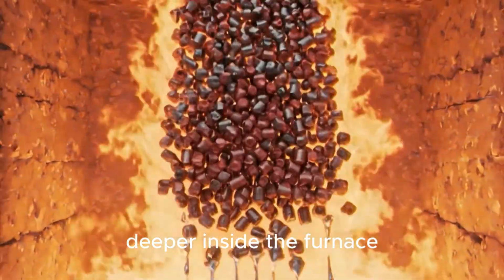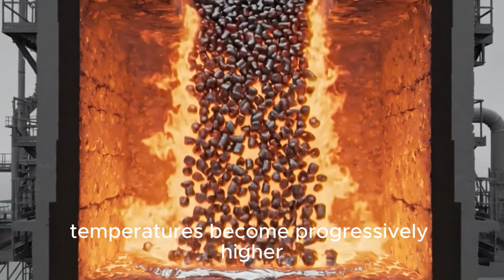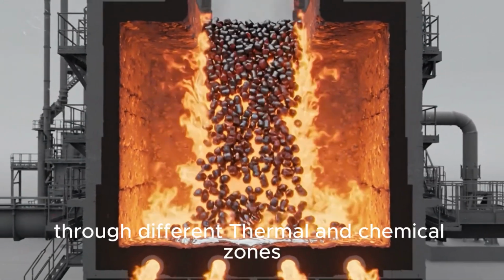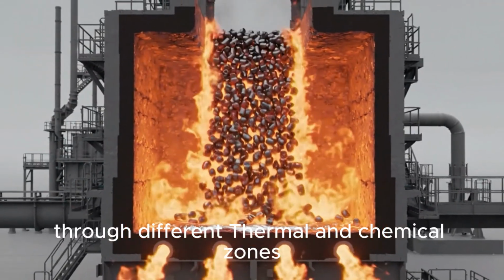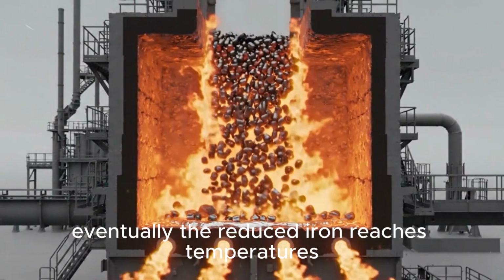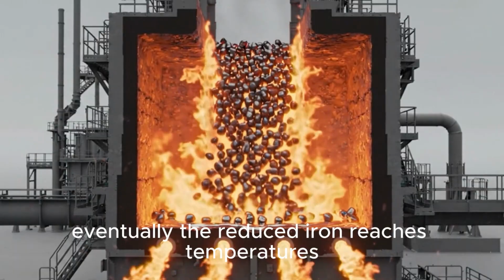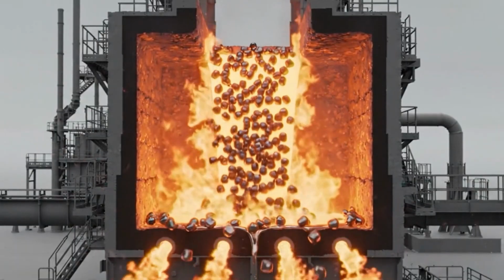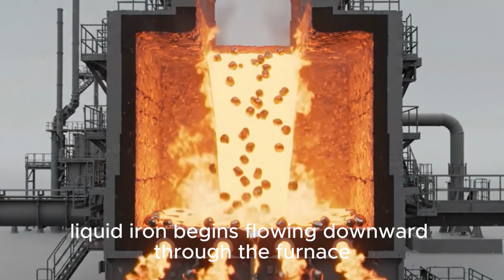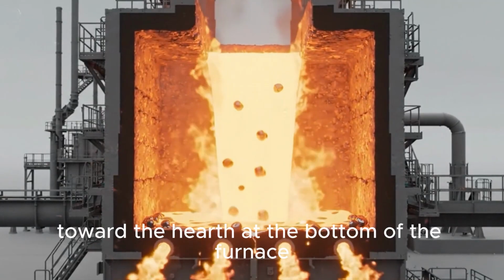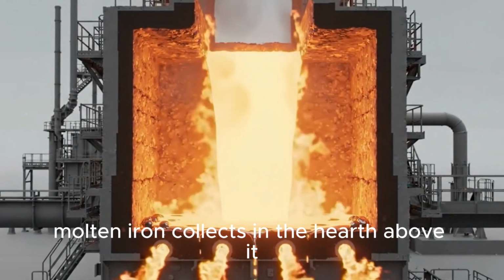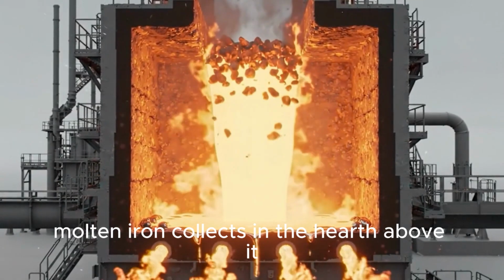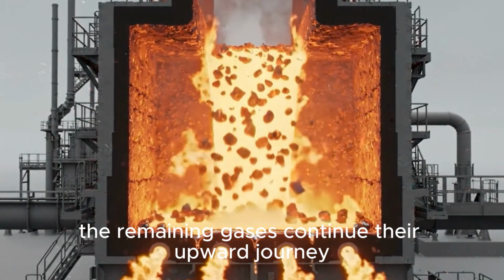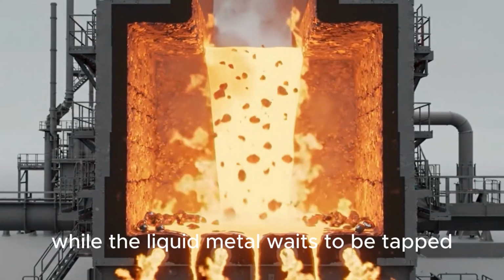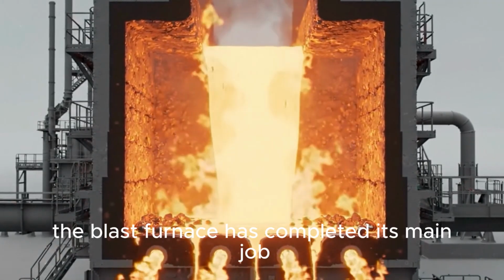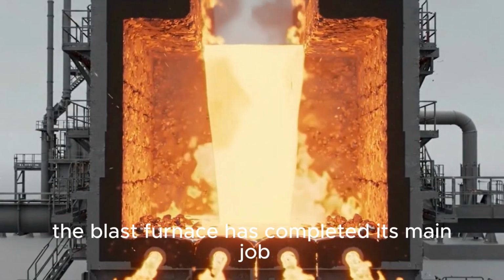Deeper inside the furnace, temperatures become progressively higher. The material passes through different thermal and chemical zones as it approaches the hearth. Eventually, the reduced iron reaches temperatures high enough to melt. Liquid iron begins flowing downward through the furnace toward the hearth. At the bottom of the furnace, molten iron collects in the hearth. Above it, the remaining gases continue their upward journey while the liquid metal waits to be tapped. The blast furnace has completed its main job.